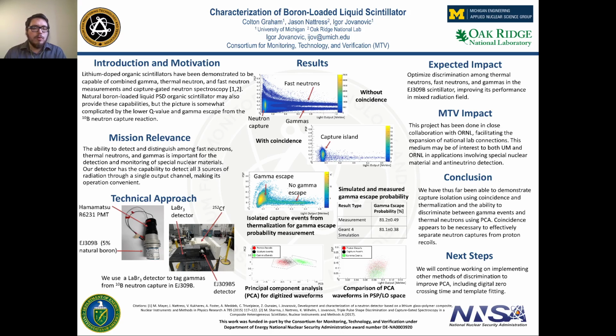It's EJ309B, which was provided to us by Oak Ridge National Lab. And you can see we've just coupled it to a PMT to measure its light output. One of the ways that we've been trying to isolate captures is by looking at coincidence from the lithium de-excitation photon in a lanthanum bromide detector. And you can see the setup for that measurement also shown on the bottom left with the lanthanum bromide detector, the EJ309B, and a californium-252 neutron gamma source.